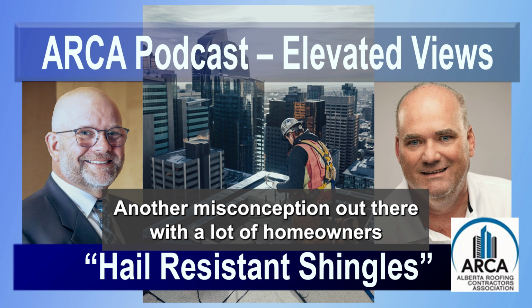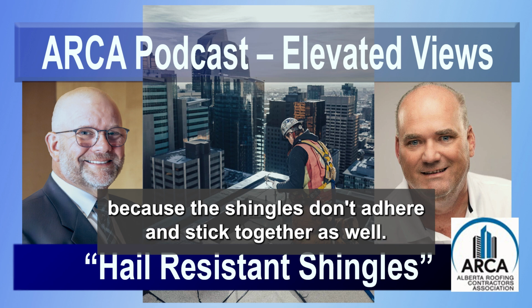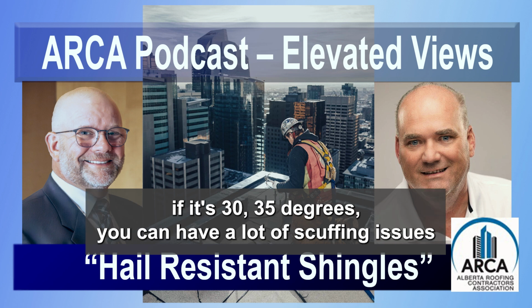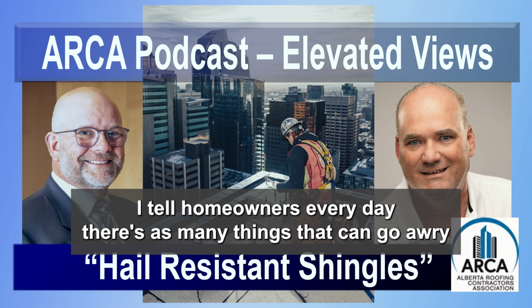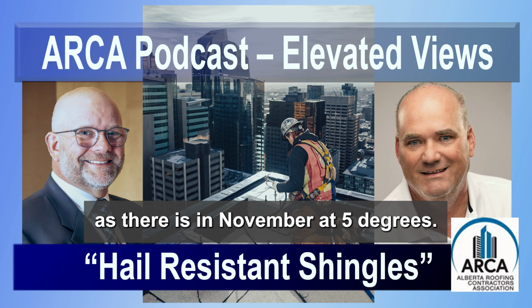Another misconception out there with a lot of homeowners is that they don't want a shingle in the cool months because the shingles don't adhere and stick together as well. The flip side of that is in June, when it's 30 degrees, or in July, if it's 30, 35 degrees, you can have a lot of scuffing issues during an installation. Really, the ideal temperature for asphalt shingle installation is probably the high teens to mid 20s. I tell homeowners every day, there are as many things that can go awry in the middle of July at 30 degrees as there are in November at 5 degrees.